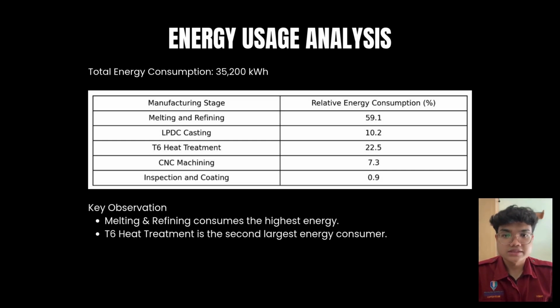Next is the energy usage analysis. The total energy consumption for the production process is approximately 35,200 kilowatt hours. Among all the manufacturing stages, the melting and refining process consumes the highest amount of energy, accounting for 59.1% of total energy usage. This is followed by T6 heat treatment at 22.5%. LPDC casting contributes 10.2%, CNC machining 7.3%, and inspection and coating only 0.9%. These results clearly show that the thermal processing operations consume the majority of the factory's energy.